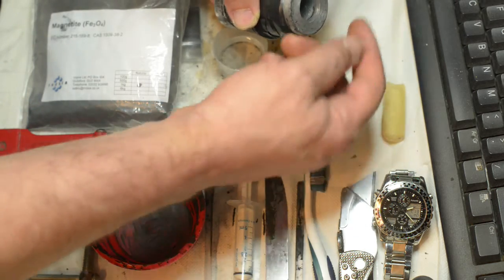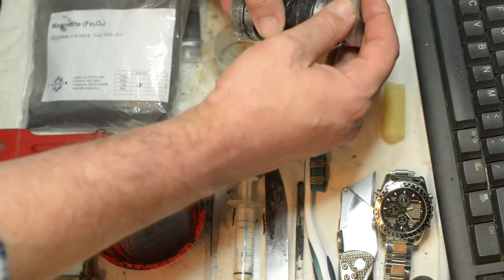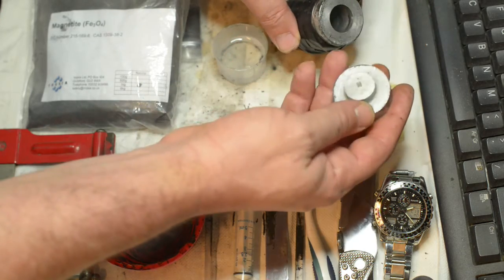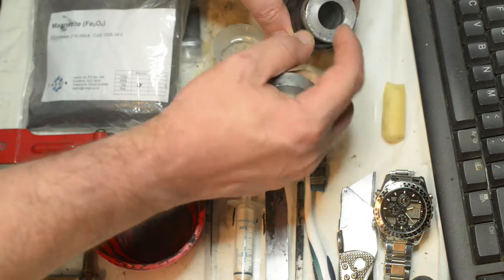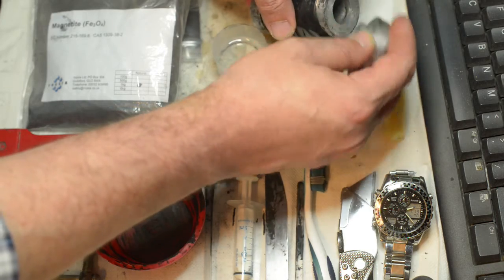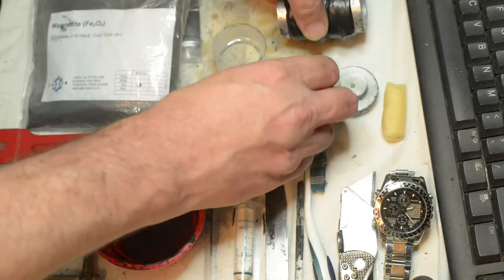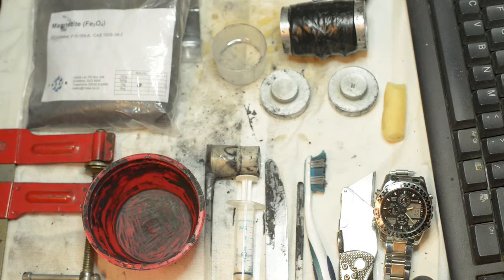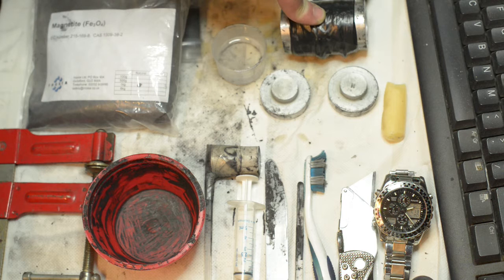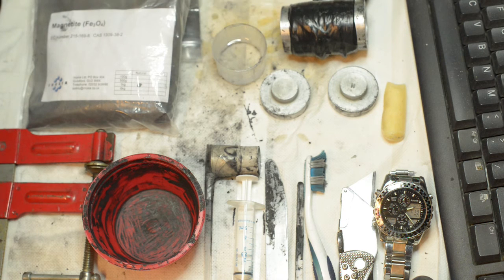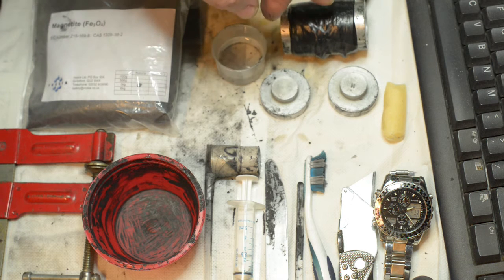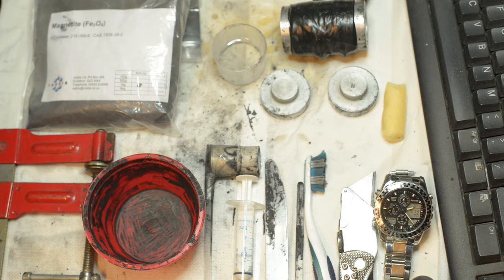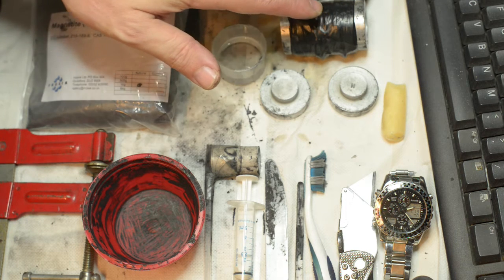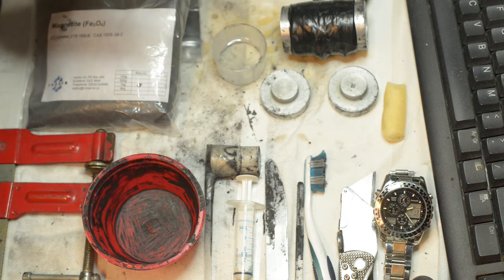End caps have been machined to match the main mold body, which fit as we see here. There is a difference between the diameter shown here on each end cap and that of the internal diameter of the main mold body. The whole point behind that small difference, 0.5 millimeters, is to allow for a gap to exist, and that is used as an avenue of escape for the contents of the mold once a given temperature and pressure have been reached. Beyond that point, the viscosity of the contents of the mold is such that no further evacuation is possible. Up to that point, the viscosity of the contents of the mold changes with temperature and pressure.